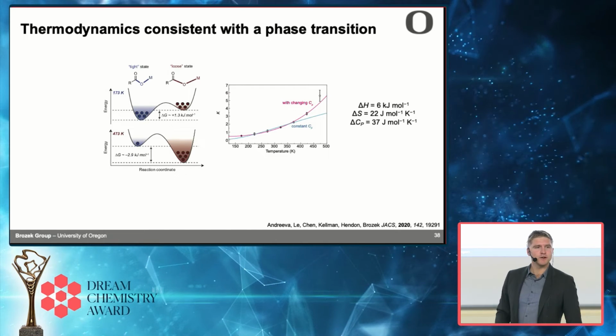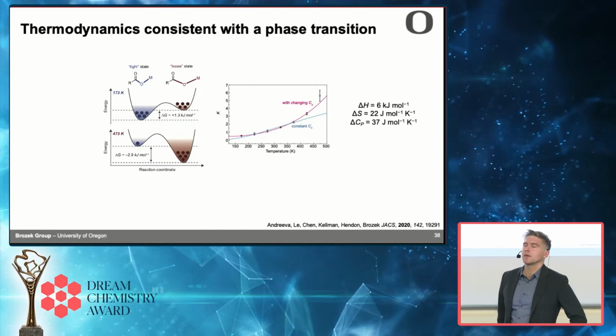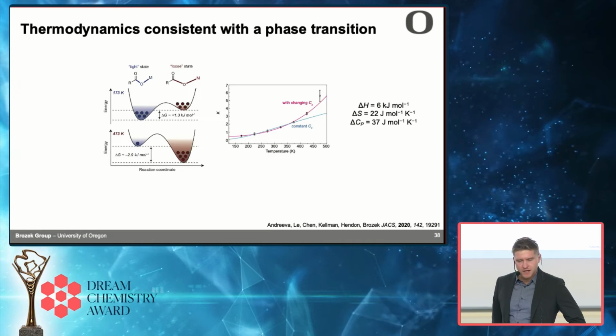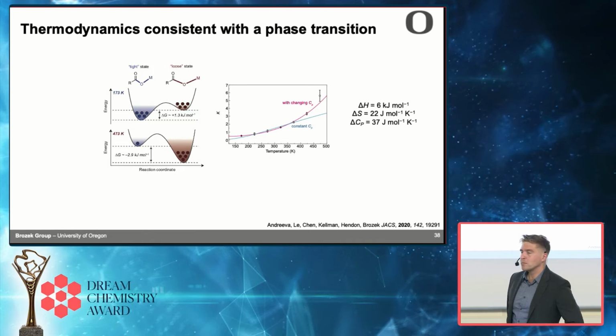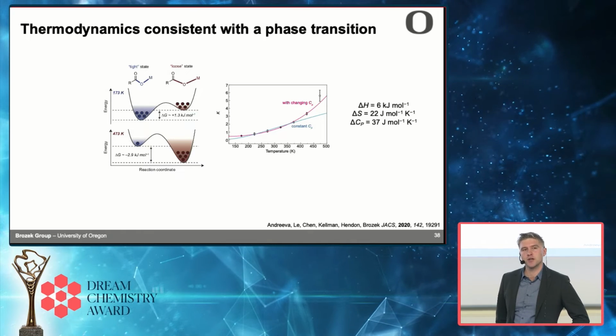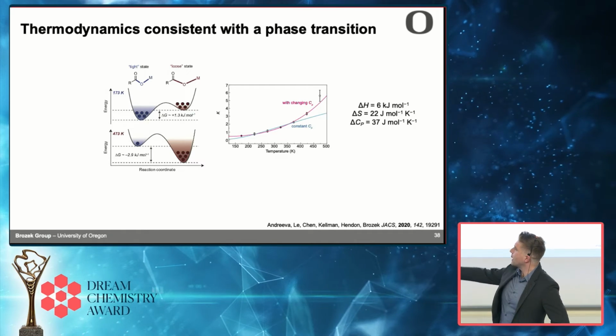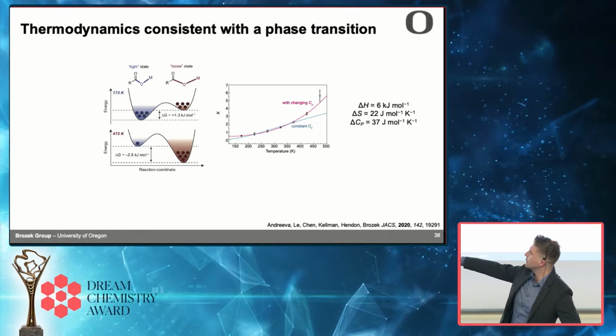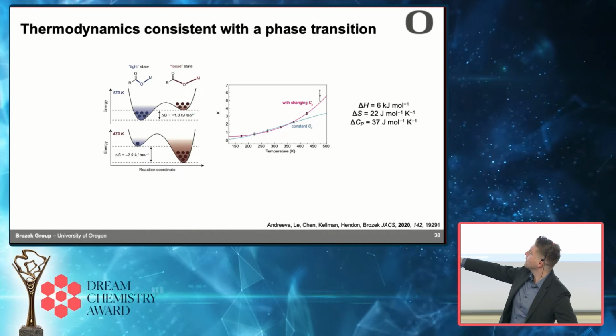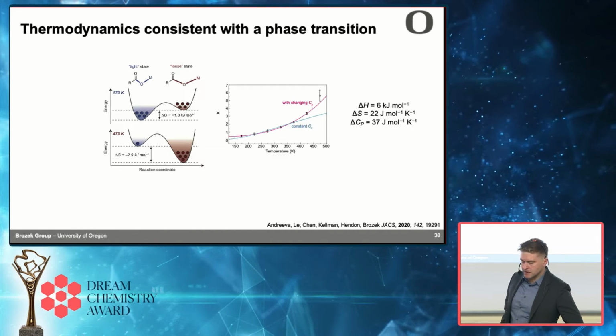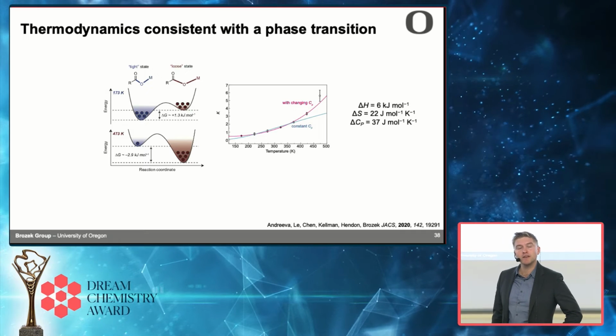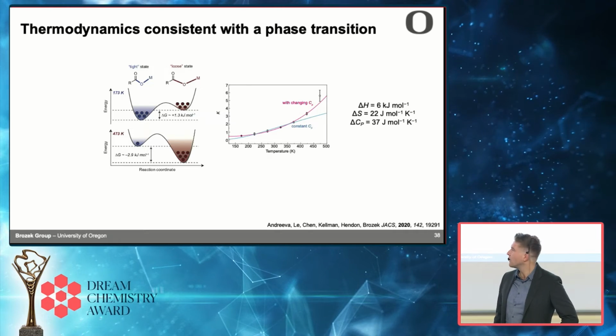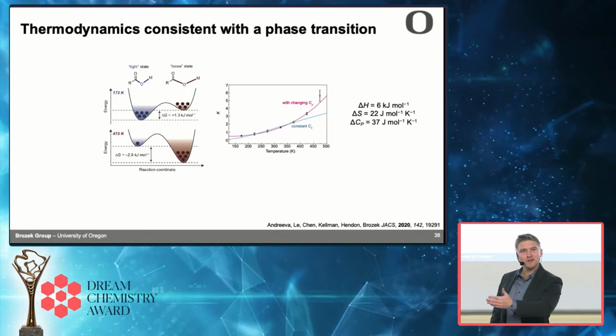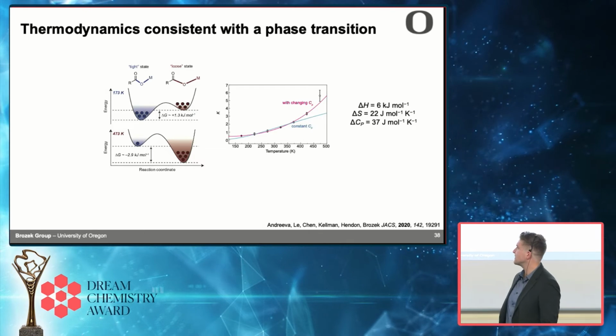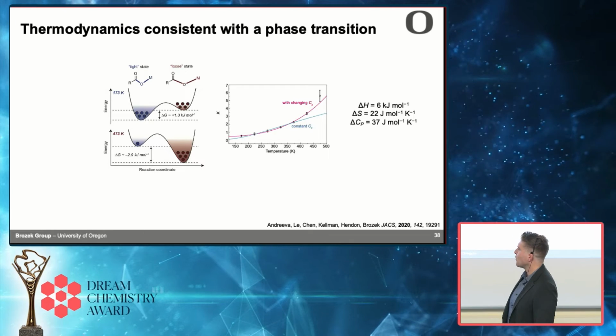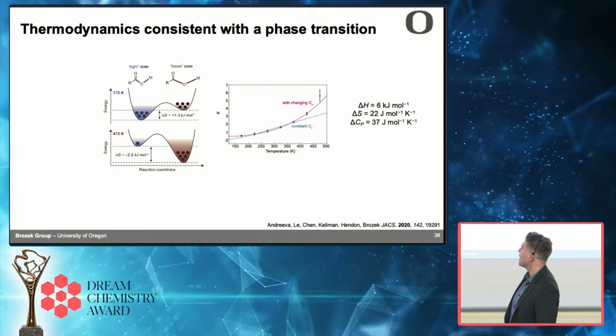And so we were looking around the literature, and it's like, what other models have people used? And there's this model where it's essentially the Van't Hoff model, but they allow the specific heat of your material to change. And so we use that, and the fit, the pink line here, is a much better fit. And this model people use to study phase change materials. So when something undergoes a phase change, the specific heat changes a lot, so you have to allow the specific heat to change, which was curious. We didn't really know why we would need to use that sort of a model.